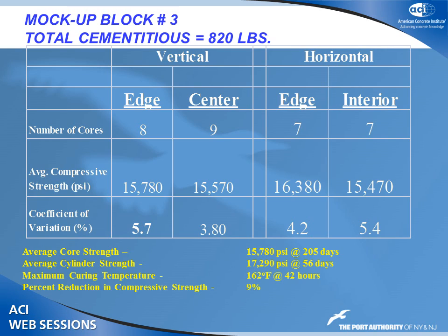That's what we got. Why? Well, maybe because it was the temperature. Maybe it was the curing. We certainly didn't cure this concrete at 68 to 78 degrees, 73 degrees, for 56 days. We didn't do that. Okay, it was certainly hotter than that. So did we take away from it? Sure. But 9%, no big deal.